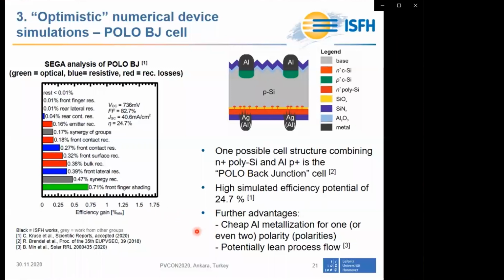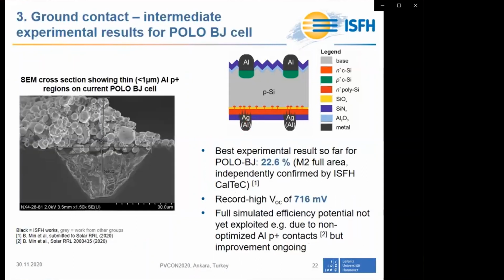Some advantages of the cell structure is that for one polarity the metallization is made of aluminum, which is cheaper than silver, of course, and we are currently also working on the metallization of the polysilicon on the rear also with aluminum, and then we would achieve a full aluminum cell. This would be very promising, and the process flow of this cell structure can potentially get quite lean.